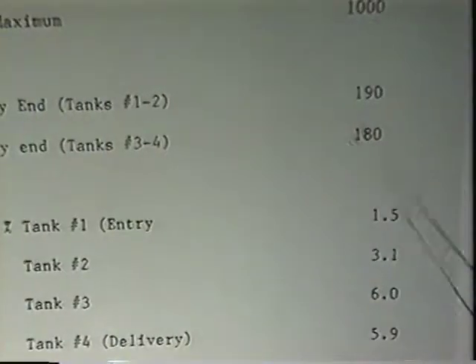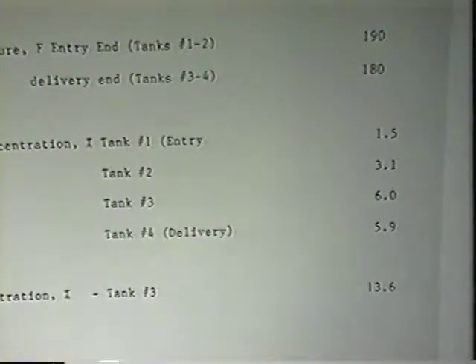And a couple more of the gotta-knows. We do carry temperature in the pickle baths, 190, 180 degrees. The hotter the acid, the greater the pickleability. The more reactive that is. You do have a problem if it gets too hot. We don't want the acid to boil. As soon as it boils, the pickleability goes down. You've got an environmental issue. So it's important to regulate the temperatures correctly. And it's also very important that you have the correct pH or acid concentration in each tank, in this thing called iron concentration. We are eating iron oxide away. The iron's going to build up in the pickle acid.